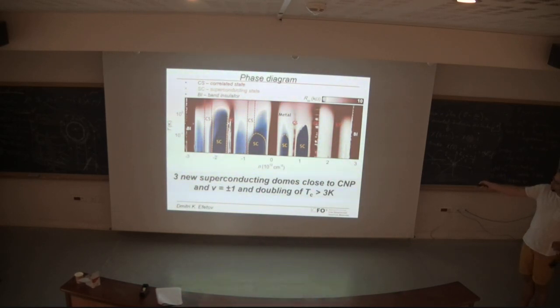Much lower. So this superconducting pocket here, which is also the pocket where Pablo observed the strongest superconducting state. In his case, TC was 1.7 Kelvin. In our case, we actually increased TC to 3 Kelvin now. And this is also the strongest superconductor here. But all the other ones are much weaker.